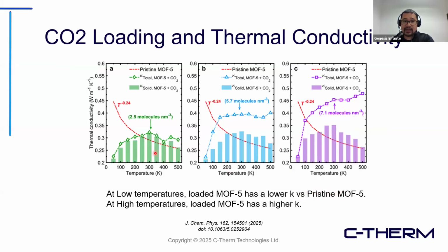Another paper right here specifically showcases how CO2 loading can have a drastic effect on the thermal conductivity of the MOF, not just the structure itself. You can see in the red line right here, these are pristine MOFs, MOF-5 specifically. And at really low temperature, what's trending here is that the MOF loaded with CO2 tends to have a low thermal conductivity, right? And then at higher temperature, you can see that it's becoming higher relative to the empty MOF, right?